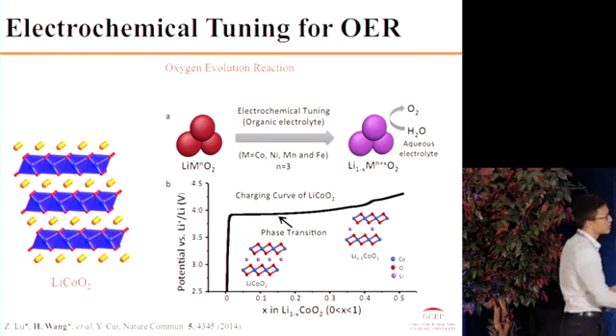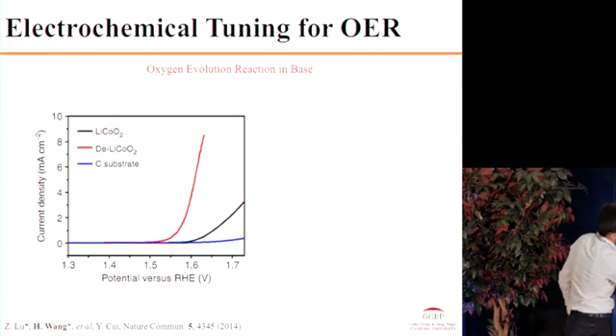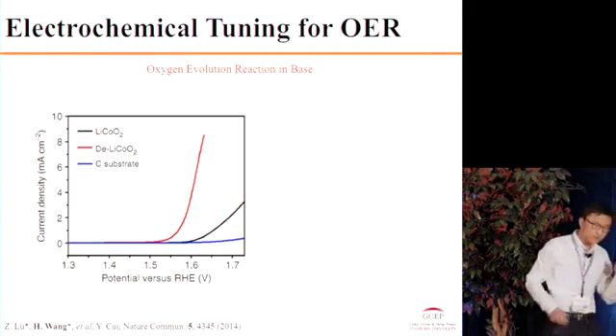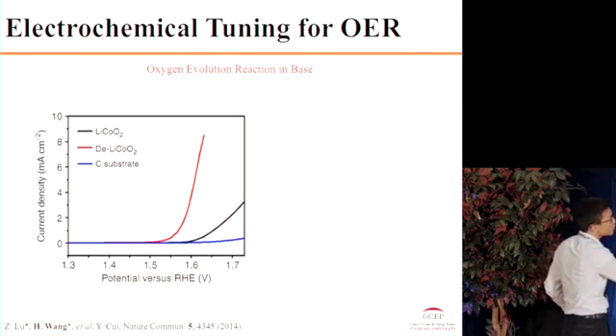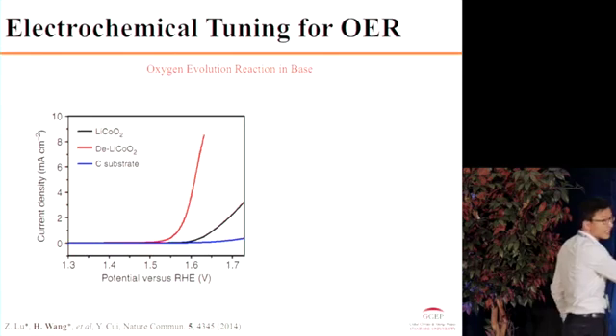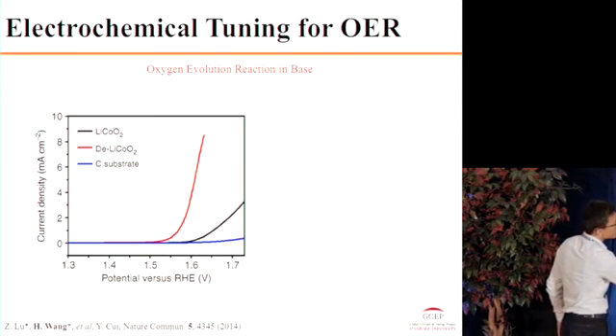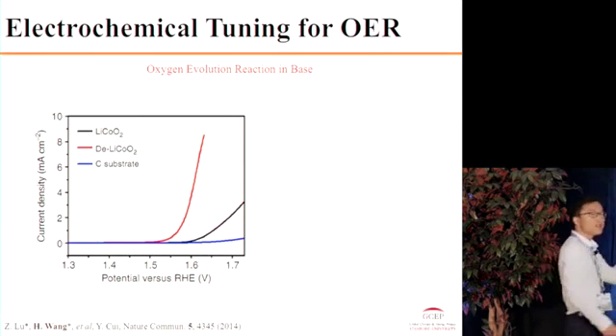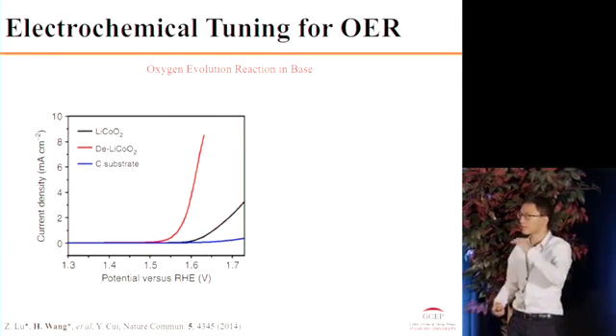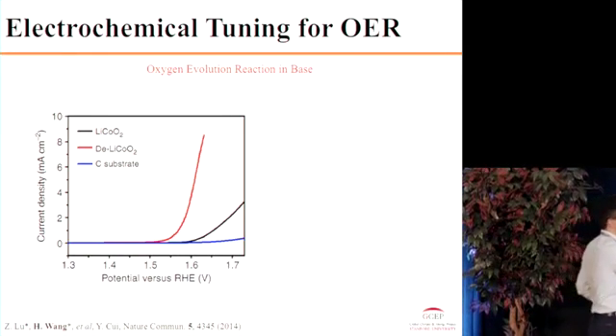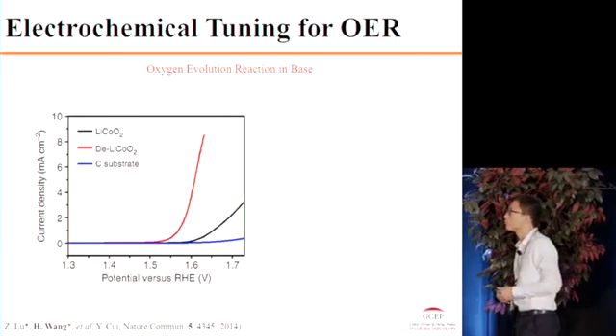As we can see from the testing result, when you extract half of the lithium, the oxygen evolution reaction catalytic activity is strongly improved. The black curve is the pristine lithium cobalt oxide. You have an onset potential around 1.6 volts. But when you do the lithium electrochemical tuning process, it's reduced to nearly 1.5 volts.